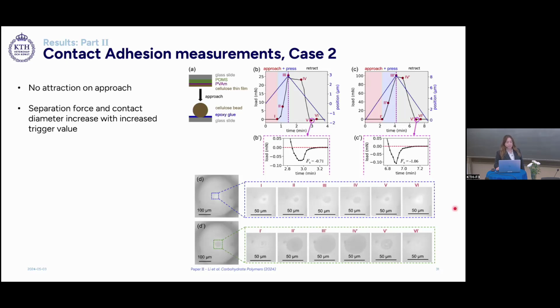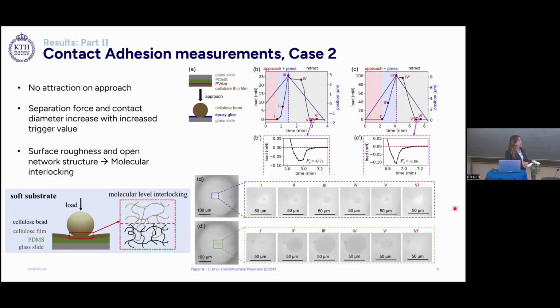Due to the slightly high surface roughness of the cellulose beads and the open network of the cellulose films, it is suggested that molecular interlocking is formed when the surfaces are kept into contact. And this is supported by the image of the contact area here, where we can see white patches, which indicate that there was material transfer upon separation. And the presence of PDMS, or a soft backing substrate of the cellulose, promotes the deformation of the surfaces, and therefore the formation of a larger contact area and ultimately larger interlocking between the surfaces.